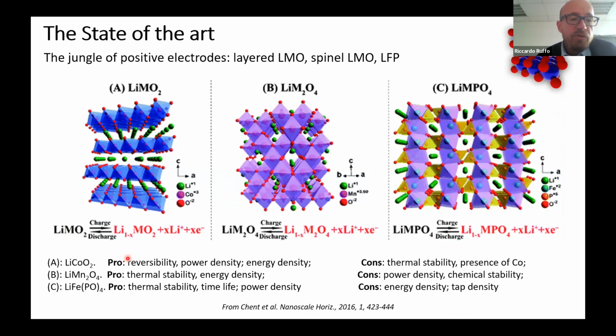The advantage of using the layered oxides is related to the reversibility and the power density, so we can run our cell at higher currents, and due to that, we can get higher energy density. However, these kinds of materials are thermally unstable, and we can have a dramatic failure of our battery, resulting in flames and explosion and so on. And of course, there is the presence of cobalt, which we want to eliminate from our batteries.